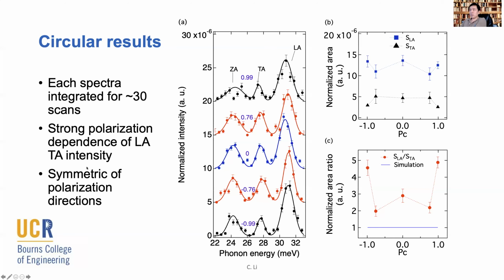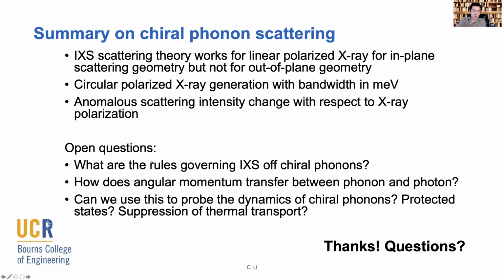Okay, so here comes the conclusion slide, the second to last part of my talk. We definitely show that we cannot use the same inelastic scattering theory people have been using for neutrons to evaluate the scattering intensity for the phonon modes. We should be able to generate circularly polarized X-rays with meV bandwidth, but it's a very difficult thing to do, and we are still not sure how good the beams are. And we do see anomalous scattering, with either linear X-rays or circularly polarized X-rays, that cannot be explained by the existing theory. So there are a lot of questions coming from this.